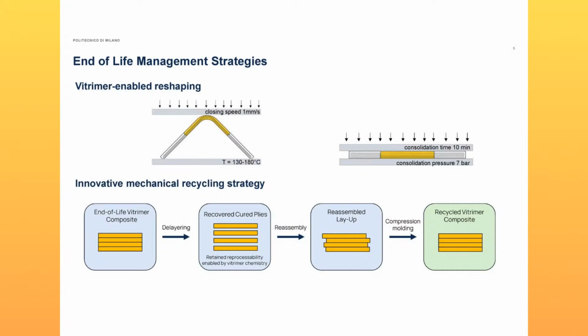Secondly, again with this concept of trying not to separate the two phases, fiber and matrix, we are trying to develop a mechanical recycling strategy. So we start from the layer structure of the composite. We are developing a technique to delayer the composite without compromising the fiber, or minimizing at least the fiber breakage. Once we obtain the individual ply, we are able then to simply reassemble them and lay up a new structure and obtain substantially a recycled vitrimer matrix composite.